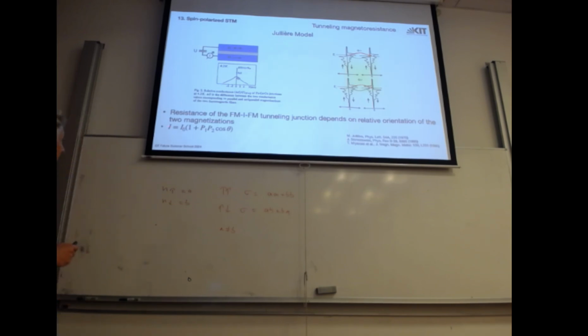I should say that the current is the unpolarized current times 1 plus P1 P2 cosine theta. P1 and P2 are the spin polarizations. So 0 means unpolarized, 1 means fully majority, minus 1 fully minority polarized. And theta is the angle between the magnetizations, or the spin polarization vectors if you like.